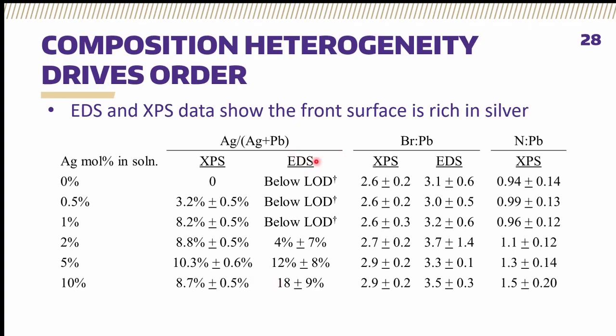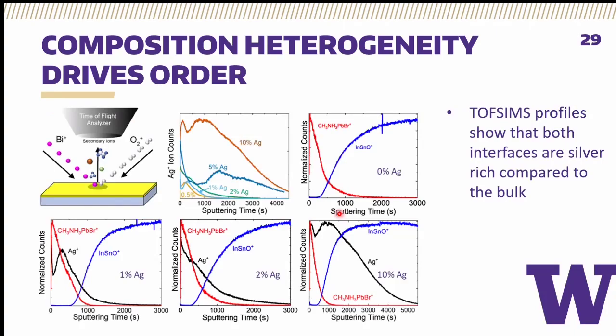EDS has a penetration depth that is long enough to get the entire bulk of our film multiple times over. It is a few microns, tens of microns in thickness, whereas our thin film is about 300 nanometers, whereas XPS is a very surface sensitive technique and only has about 10 nanometers of penetration depth. Therefore it is only probing the elemental composition of silver very near to the front interface of our thin film. Up to 5% silver incorporation, our XPS counts of silver are much higher than our EDS counts, showing that, at least in these samples, we have preferential silver segregation to the specific interfaces of our thin film. Now, that's less important than the back interface, which potentially could be even more important in driving this order.